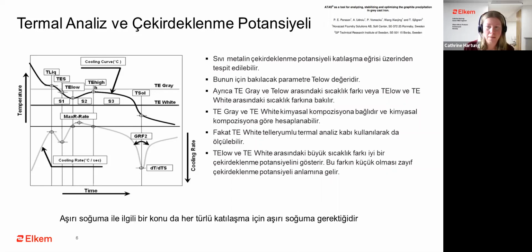the TE low. And the TE gray here represents the eutectic stable line, while the TE white represents the metastable line. Now, the nucleation potential is then the temperature difference between the TE low and the TE white line, or you can measure it versus the TE gray line. Now, both TE gray and TE white are a product of chemistry, and can be calculated if you have the chemistry. But TE white can also be determined by using a tellurium cup, and you can always pour a white cup or a tellurium cup, and you will have the TE white.